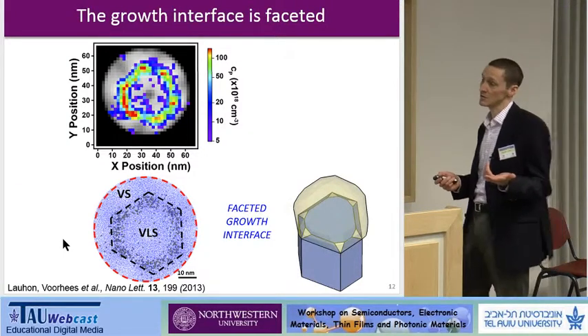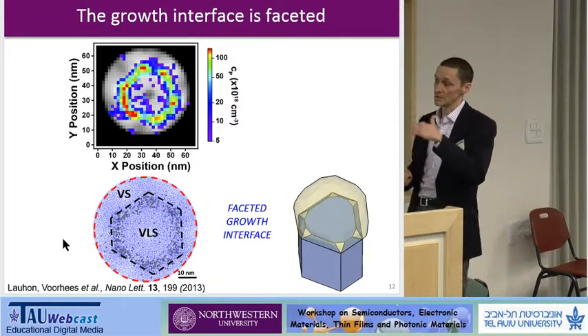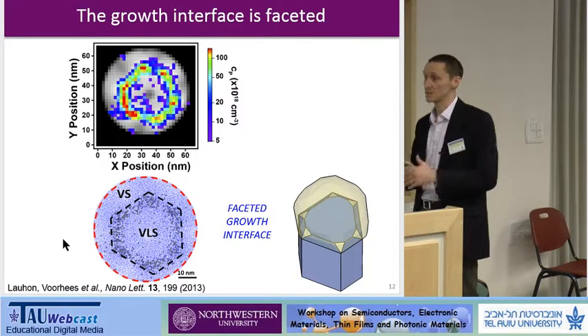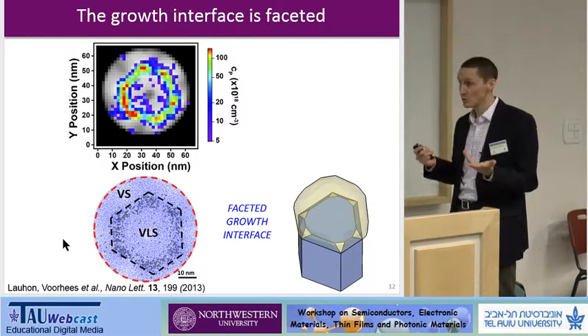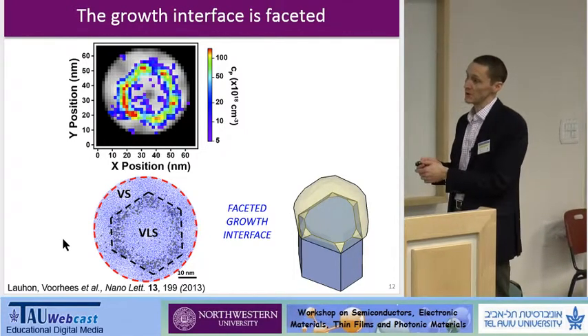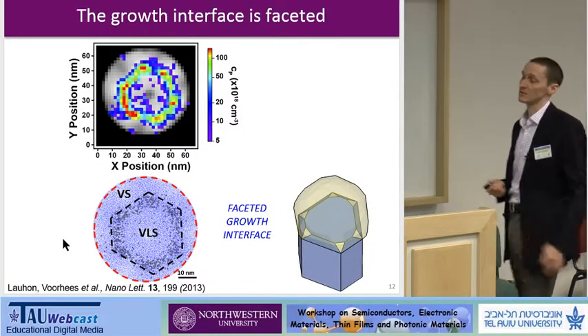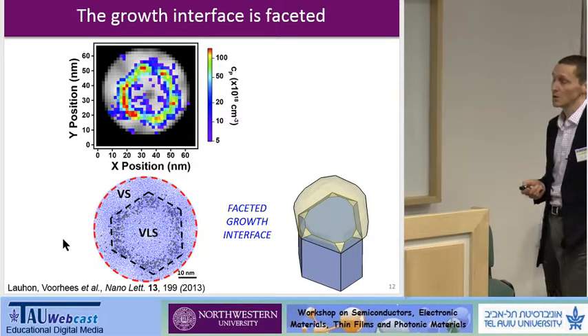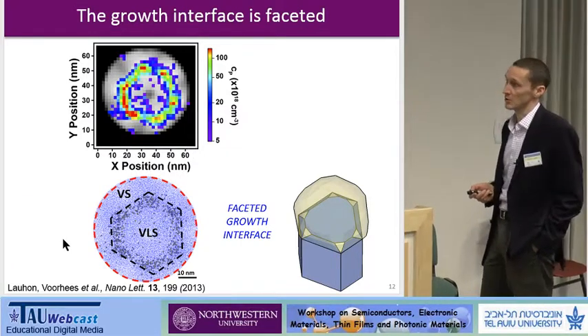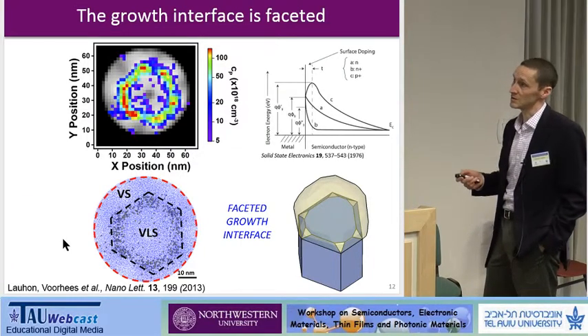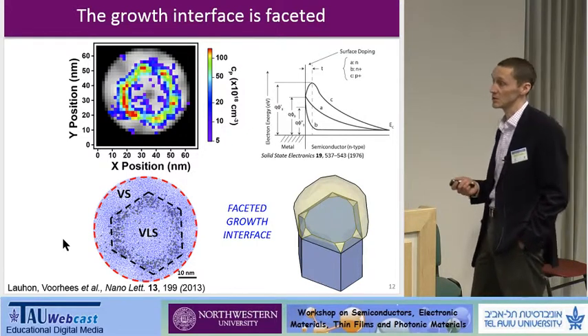And what we came to understand is that the growth interface is not this single 1-1-1 interface, as we thought in sort of the cartoon form. It actually has multiple facets. And so the dopant incorporation rate depends on which facet the dopant is coming in through. So of interest, in particular to those making devices, is that this is an enhanced surface doping, essentially.